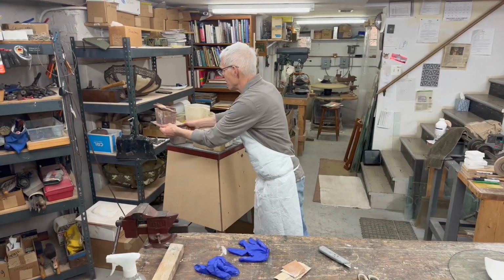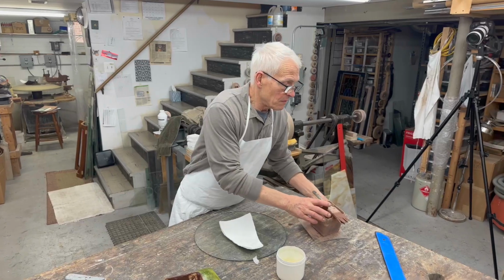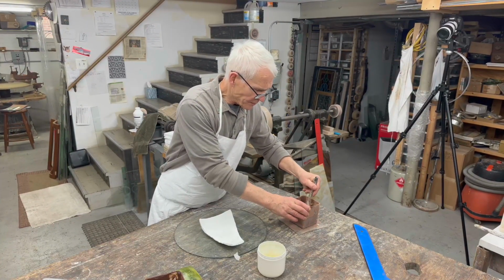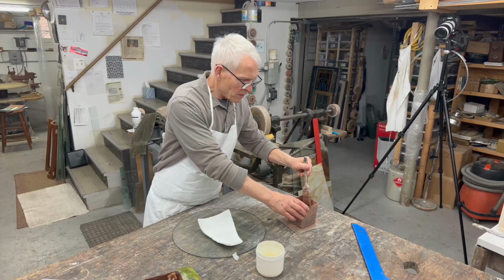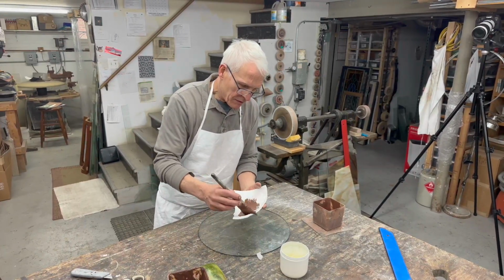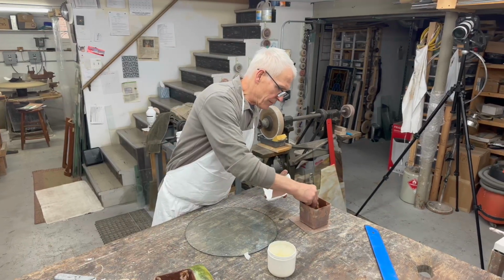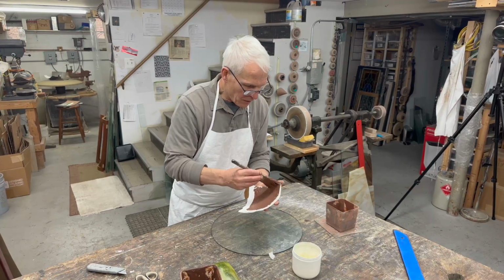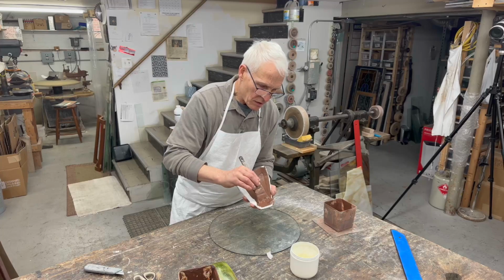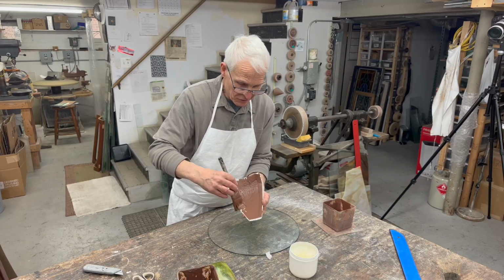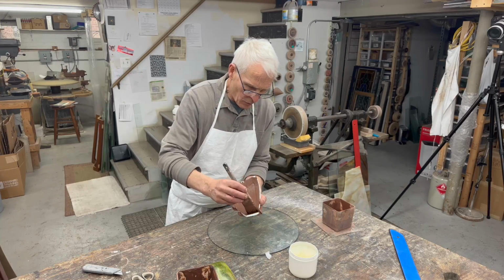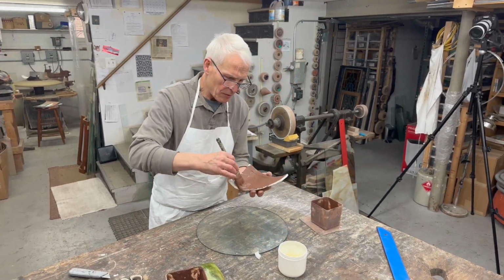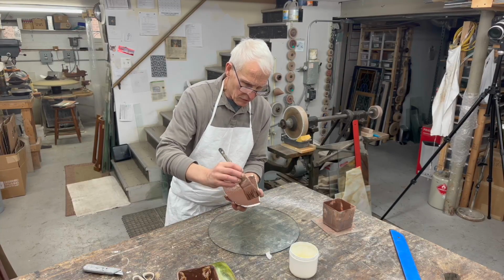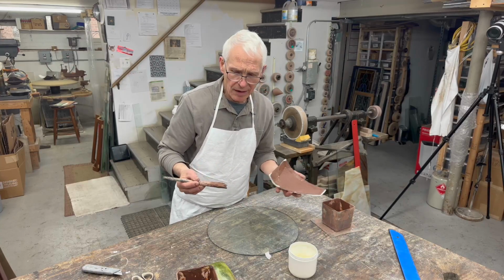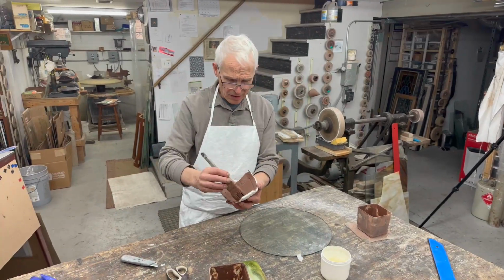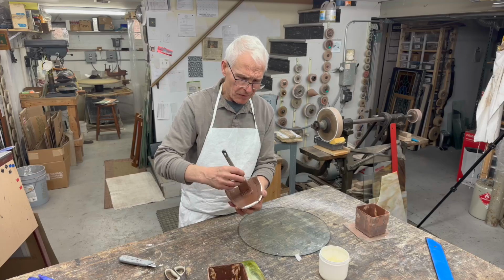So what I typically use, which isn't something that's real common, is a ceramic slip, and it's thicker than kiln wash. It fills in a lot of the voids. There's quite a few artisans that use this. I don't get too carried away with sanding it because of the fiber dust and everything. Like I said, this is a ceramic slip. It's called Albany slip, I believe. You might not find that exact product, but something similar is available.